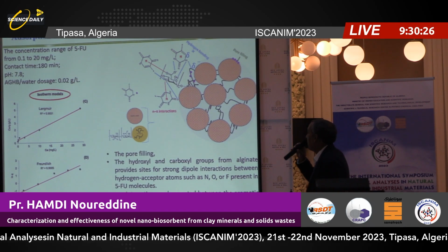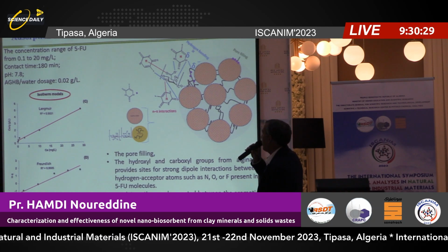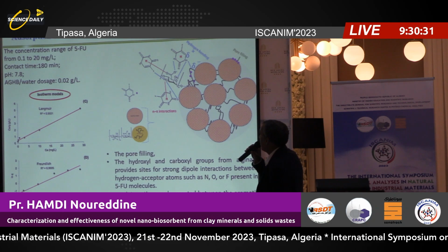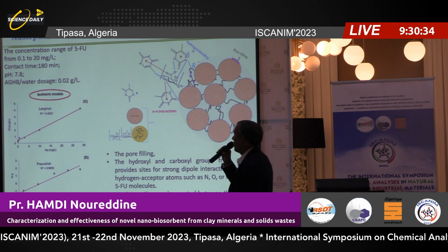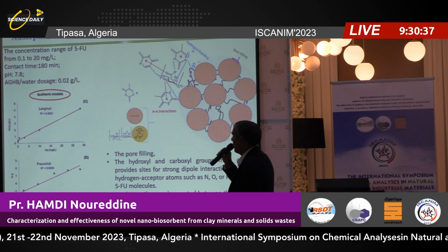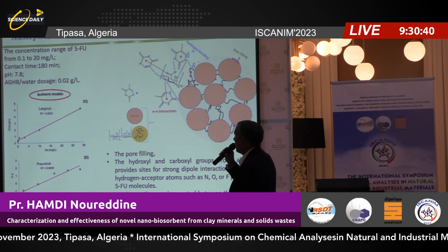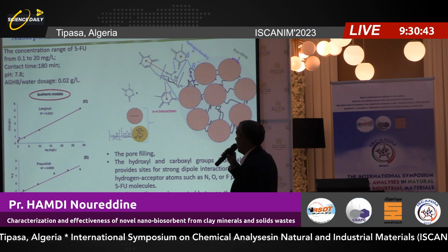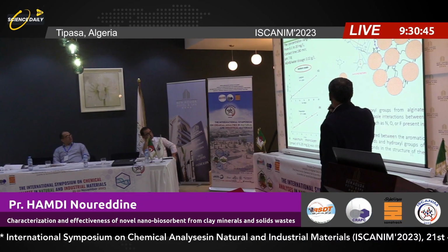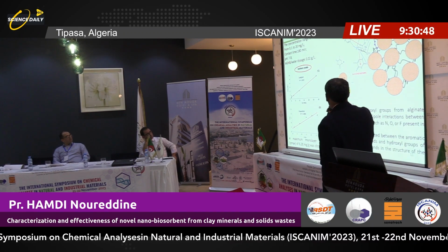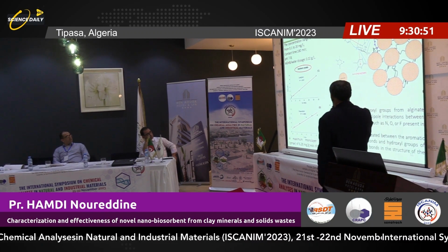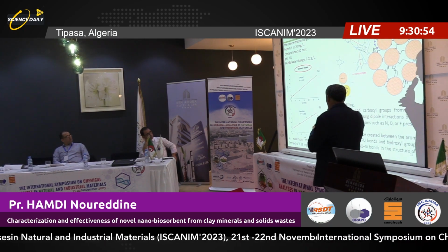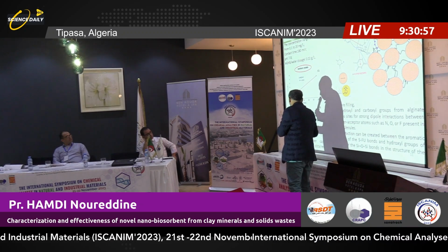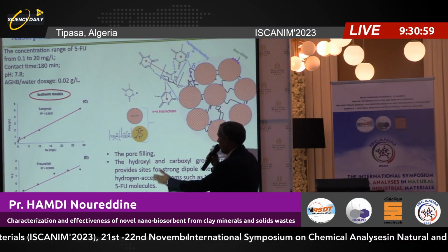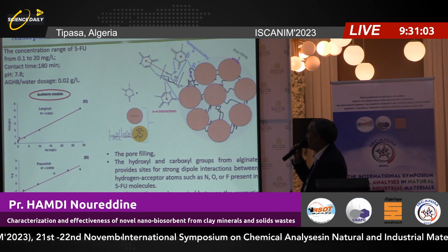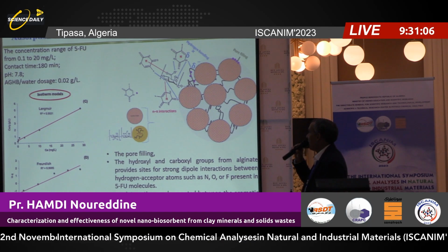Now the adsorption protocol. The experimental concentration is about 0.1 to 20 milligrams per liter. The contact time is about 3 hours, pH 7.8, and the solid-liquid ratio is about 0.02. The adsorption data are modelized by Langmuir and Freundlich models, and the maximum of adsorption is 6.2 milligrams per gram. This is a very, very huge adsorption because this pollutant is not adsorbed by the mineral.